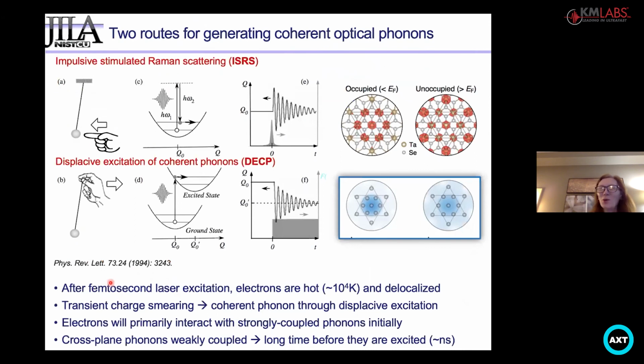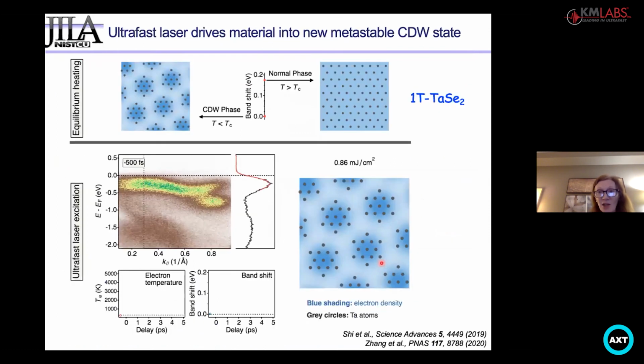Because the charge density wave order is in the ground state, the electron orbitals in the charge density wave state are located around, I mean, they screen the atoms and give rise to this beautiful order. But the excited state orbitals are delocalized. And so when you heat this material with a femtosecond laser, you promote electrons from the occupied to the unoccupied states, and they very beautifully excite a coherent phonon or a breathing mode of that Star of David. And that's been seen before, and so that is not new.